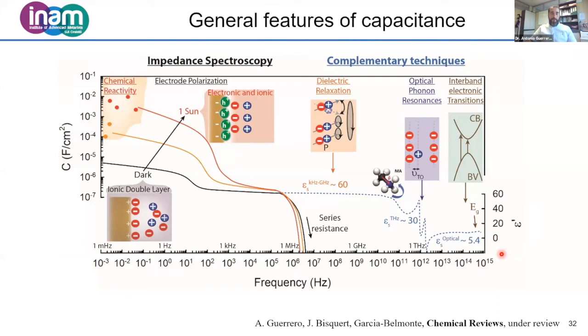feature of our material. As we apply the alternating electrical field, and it takes longer to apply this electrical field, not only do we change how the methyl ammonium molecules reorient, but we promote ionic migration inside the perovskite material. So this onset in capacitance, where we see an increase, is because the bulk material begins to change, and ions begin to go to the contacts. And at very low frequencies, there will be an ionic double layer close to the contact, and then we are probing the properties of the contact.